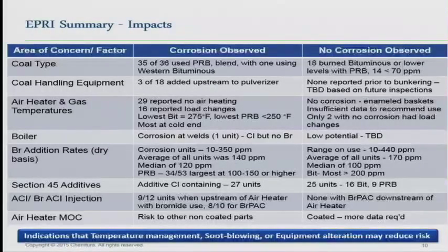On the coal handling equipment, 3 of 18 where they added upstream of the pulverizer showed some corrosion. They weren't quite sure what happened there. Where they did not see corrosion is where it was added prior to bunkering. However, they did state that they really hadn't had all the inspections, so they were pending some future inspections on the bunker areas.